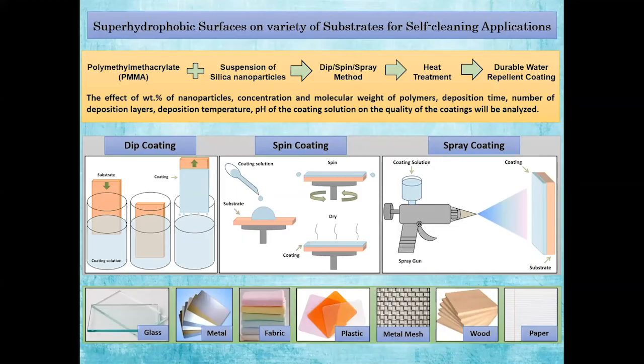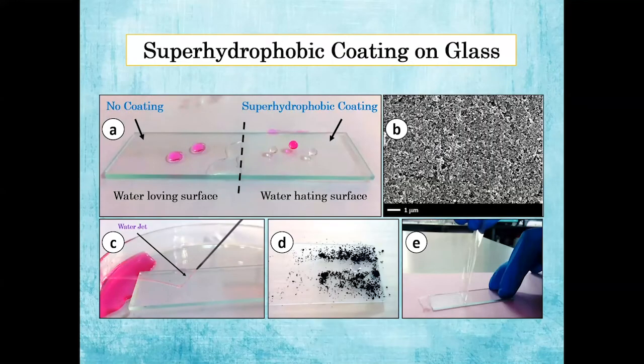So first we tried on the normal glass surface. You can see half of the glass surface was coated with this PMMA silica nanoparticle, and half is not coated, and you can see the water behavior on both surfaces. On the non-coated part, it is wetting, and on the coated part the water drops are like cricket balls, ball-like structure, perfectly round.